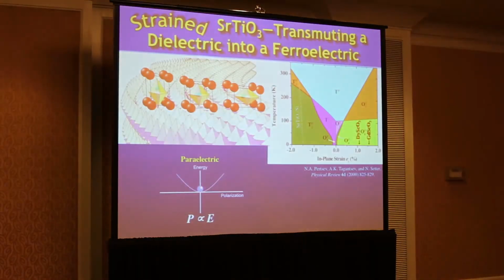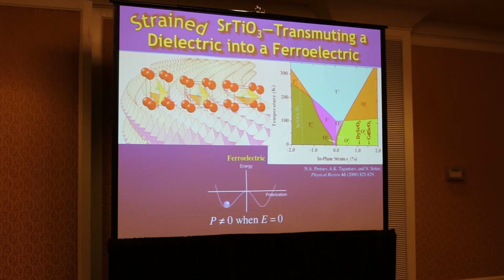Okay, now that's just, whoa, I pushed a bad button. Okay. Let me just show you an example of that. So here's a nice, boring titanium sitting in the center of this cubic strontium titanate, a boring textbook dielectric. But if you stretch that box, the titanium would like to rattle around inside the cage. So from an energy perspective, the energy landscape of the titanium looks like this. It looks like a double well, classic for a ferroelectric.